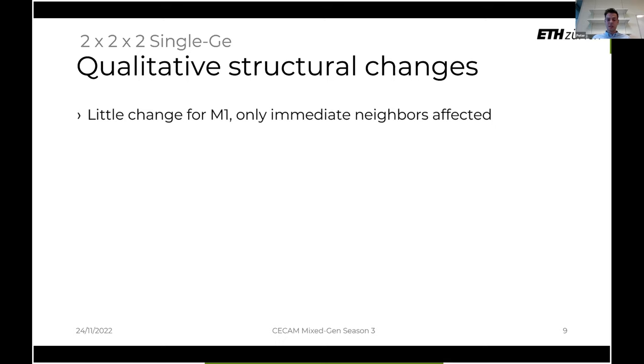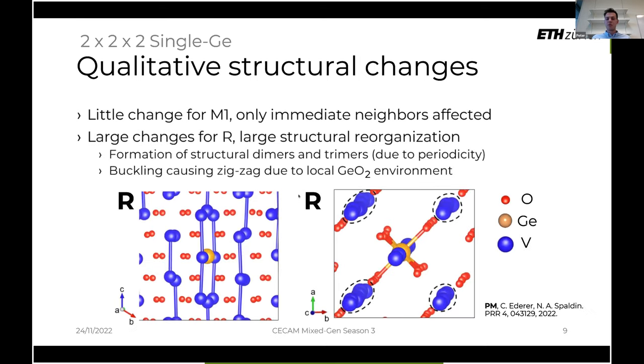In the monoclinic phase, which is the dimerized one, we don't really see much. We only see immediate neighbors being affected. But in the rutile phase, we see large structural reorganization. So in fact, I'm showing you two details of the resultant geometry optimized structure, where the yellow dot is the germanium. Now, if you remember, the vanadium chains are going along the C direction, so this way. Once we add the germanium, we observe a formation of dimers, here indicated by these bonds, and also formation of structural trimers, which are due to the periodicity of the cell being too small. And indeed, this is one of the reasons why we moved on to a larger cell.